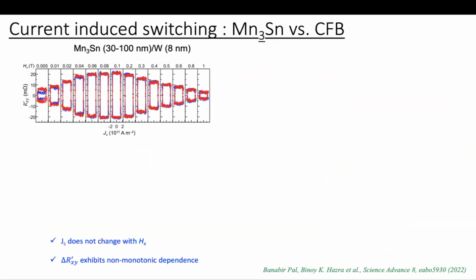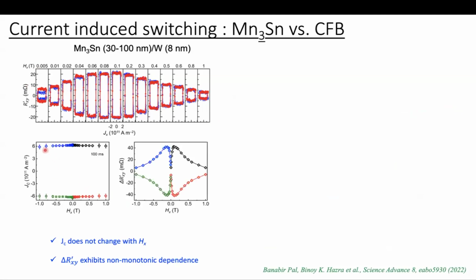We apply different bias fields starting from 50 oersted. When the bias field is small, the current-induced switching magnitude, or the change in the Hall resistance, is small. As we increase the bias field, the switching magnitude increases, and then beyond 0.1 Tesla, the switching magnitude decreases, as does the Hall resistance. From here, we extracted the current density and the change in the Hall resistance and plotted them here. The current density is independent of the bias field, whereas the change in the Hall resistance shows a non-monotonic behavior. Initially it increases, reaches a maximum, and then again decreases.